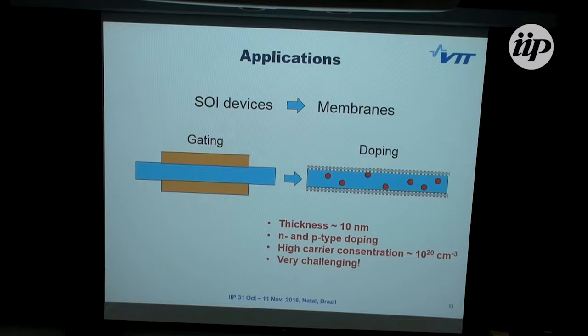Here the problem, of course, is that when we are talking about freestanding membranes, we cannot use gates. So we have to bring in the carriers through doping, and when the thickness is, let's say, below 50 or around 20 nanometers, this doping is extremely difficult. Especially when one has to have P and N type doping in the same membrane, it's technically very challenging. And the aim is, as said, to go close to 10 to the 20th per cubic centimeter carrier concentration, both P and N.